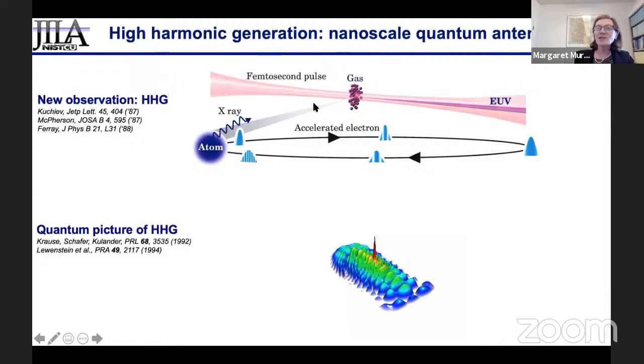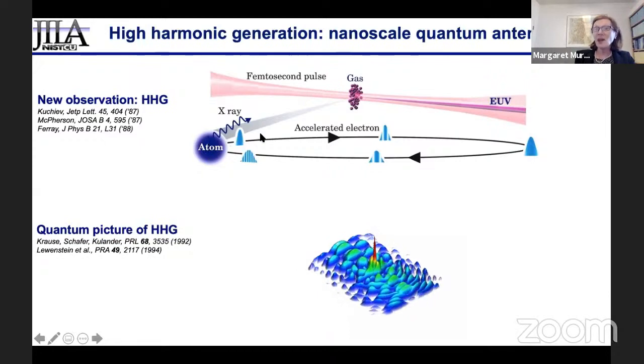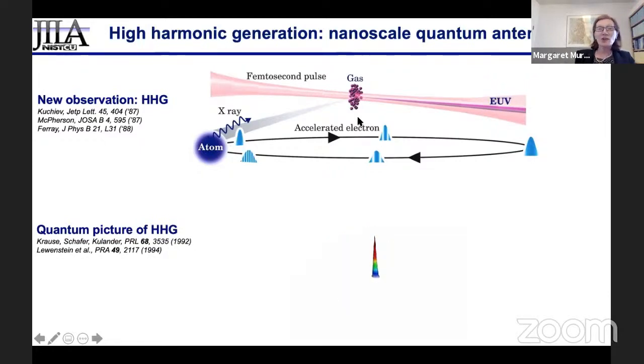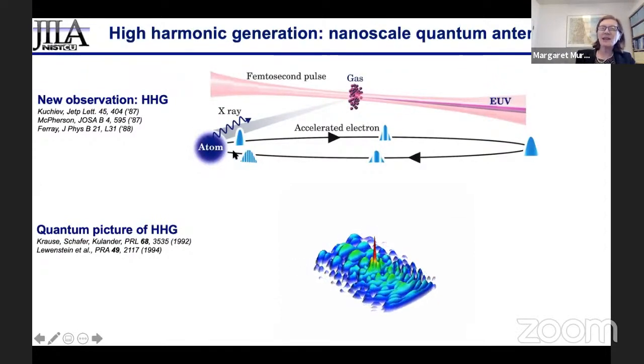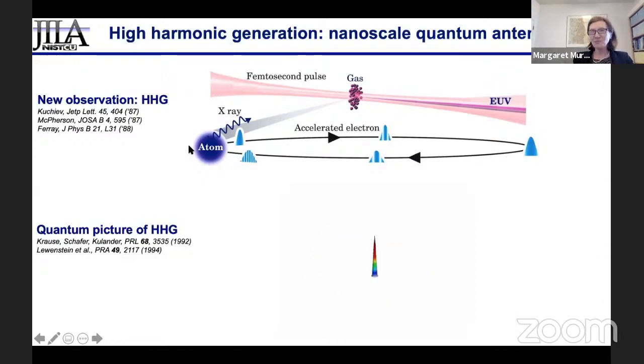If you just look at this top figure here for now, under the action of this intense laser field, you don't need much energy, but if your pulse duration is short, the field is higher than the field that binds the electron to an atom. So the atom can ionize, the laser field is stronger than the Coulomb field, and that drives the electron away from the parent ion. And when the laser field reverses, the electron can return, recombine, and liberate its energy as an X-ray. So in that cartoon on the top,